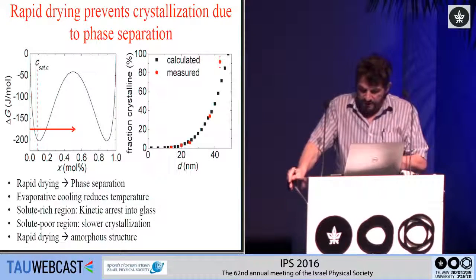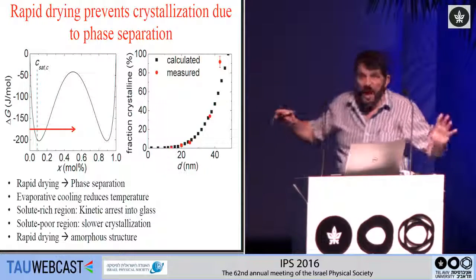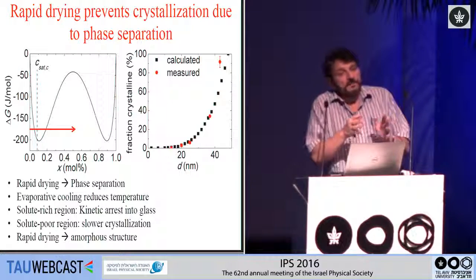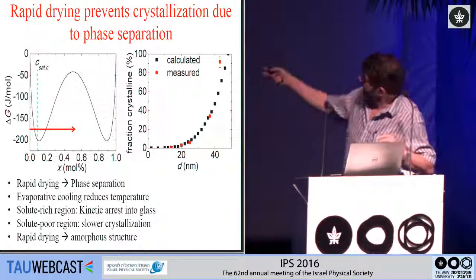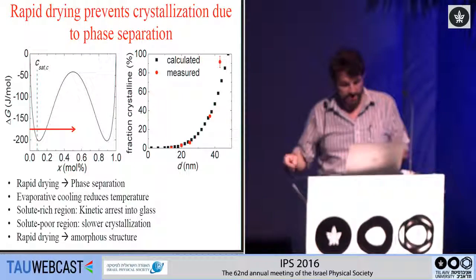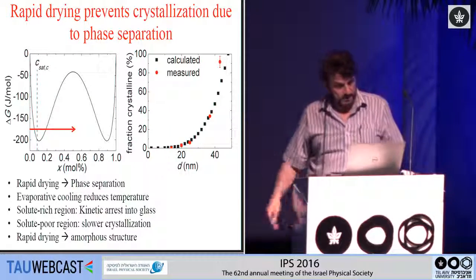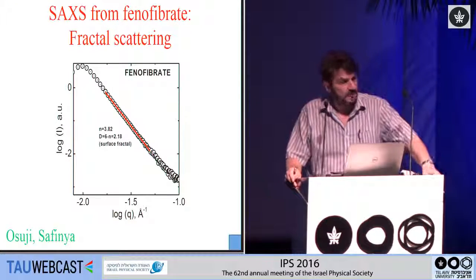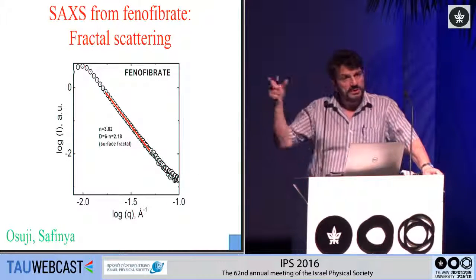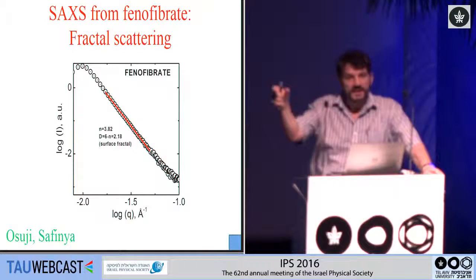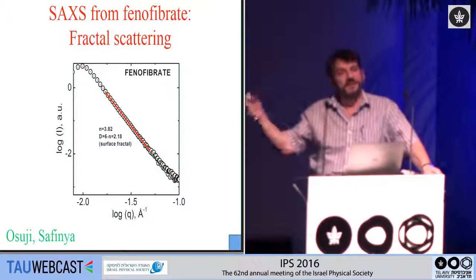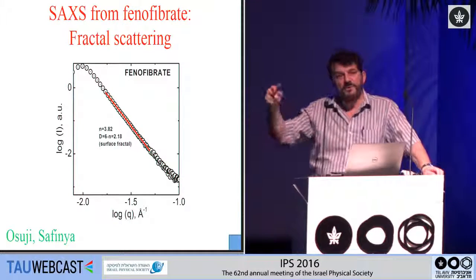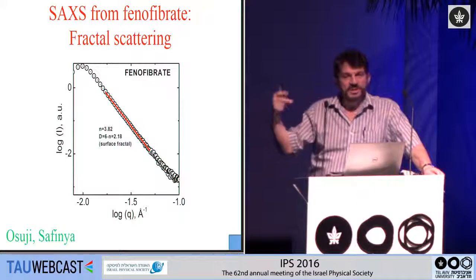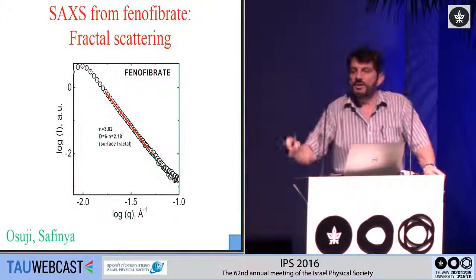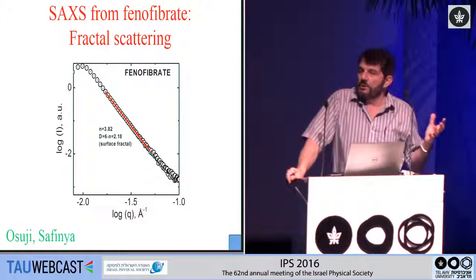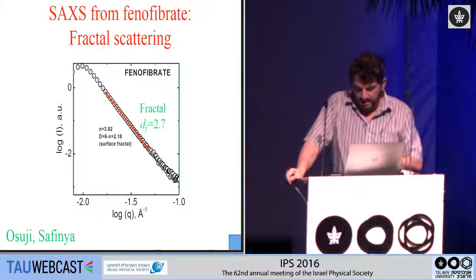And in fact, you can do some simple calculations. I won't go through them. You make one assumption about the surface tension, and you can predict the fraction of particles that actually crystallize. It's very consistent with what you observe. You also can do some X-ray scattering to look inside the structure of the particles, and you find that they're also not solid, but rather they're fractal-like, exactly as you would expect if they were formed originally by some kind of spinodal decomposition.